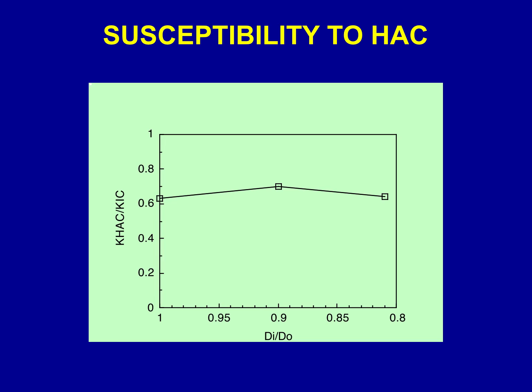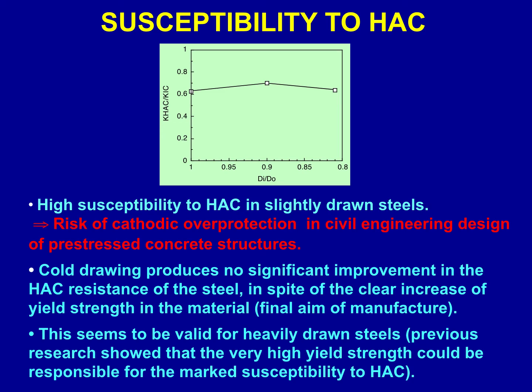Discussion. With regard to the susceptibility to hydrogen-assisted cracking, there is a clear effect of hydrogen, so that for slightly drawn steels behaving in isotropic manner in mode 1, we can evaluate the critical K in hydrogen embrittlement, hydrogen-assisted cracking conditions divided by K1C versus the degree of cold drawing, and there is a marked reduction as a consequence of hydrogen. It means a high susceptibility to hydrogen-assisted cracking in slightly drawn steels. This means risk of cathodic overprotection in civil engineering design of pre-stressed concrete structures.